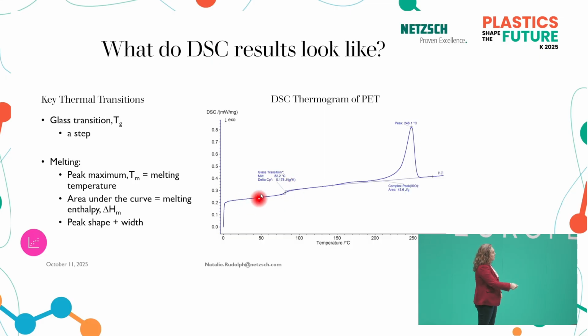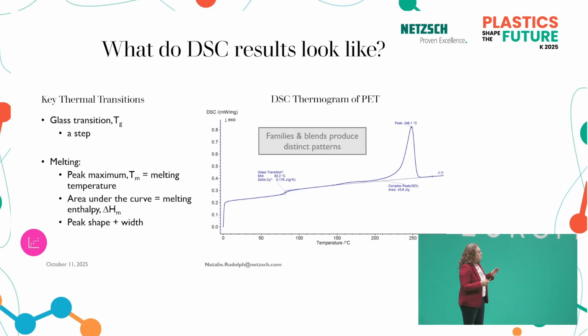We can learn something from this little step in the curve that's related to the glass transition, and the higher that is, the more amorphous is a material. And then we learn from this peak. So we learn from the peak temperature, so the highest point. We learn from the onset, endset, the area underneath. All of these features of the curve are relevant in order to understand the fingerprint of a material. And families and blends produce distinct patterns that we can look for.